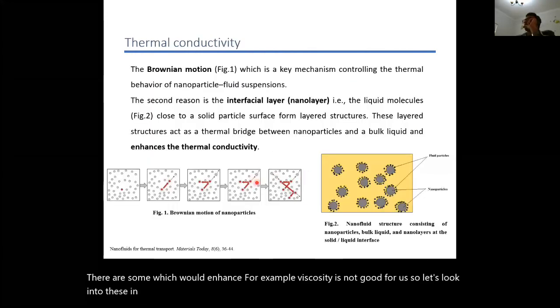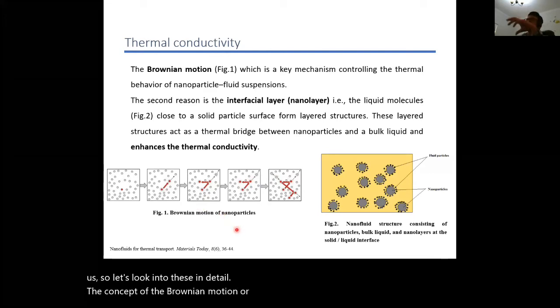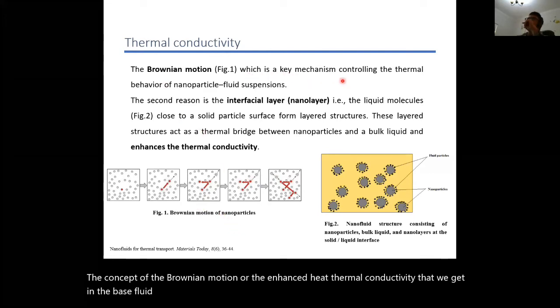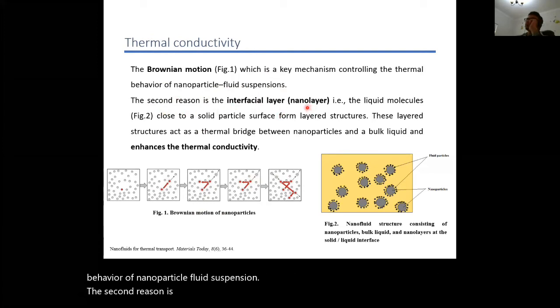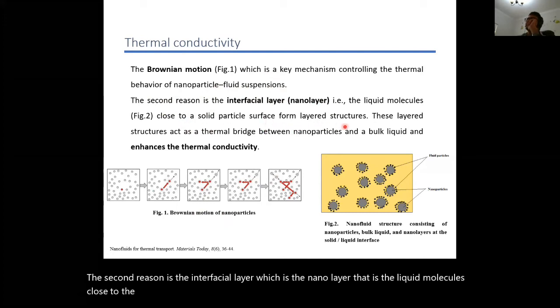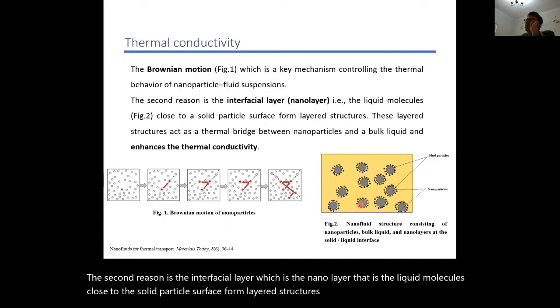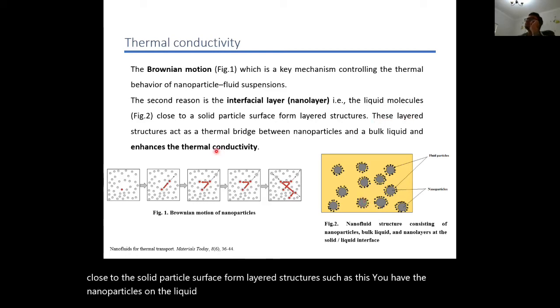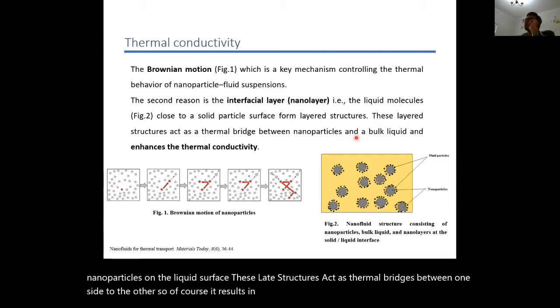The concept of the enhanced thermal conductivity that we get in the base fluid is, first, the Brownian motion, which is the key mechanism controlling the thermal behavior of nanoparticle fluid suspension. The second reason is the interfacial layer, which is the nano layer, that is, the liquid molecules close to the solid particle surface form layered structures, such as this. You have the nanoparticles on the liquid surface. These layered structures act as thermal bridges between one side to the other. So, of course, it results in better heat transfer between the nanoparticles and bulk liquid,